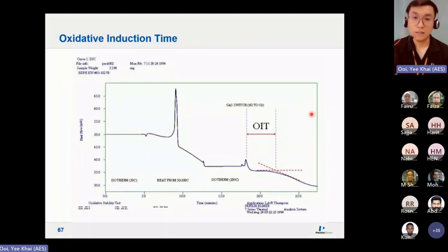Okay, this is OIT. It's a standard test for polyolefins. It measures how long the polymer can withstand oxygen attack before it gets oxidized. The method states that oxygen is required, and this is an open pan analysis because you need oxygen to come into contact with the polymer itself. So of course you heat up, the material melts, and then isothermal.